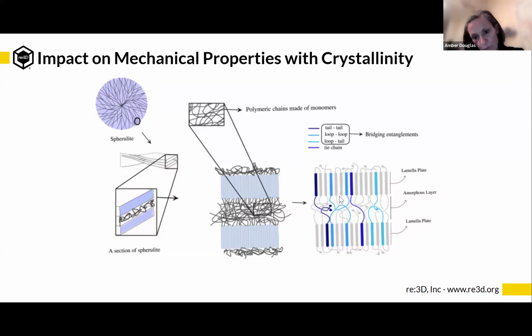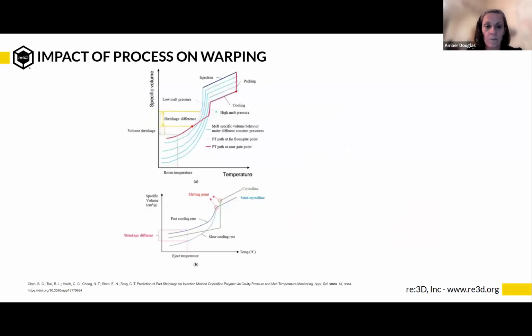But if you imagine trying to break that or pull that apart and do elongation, it's going to act like a crosslink almost. It's not going to break as easy as amorphous. I included this because this is how your process can affect your crystallinity, and they show different parameters that they've set things to. For example, they have fast cooling rate, slow cooling rate down here. And almost anything that you do with temperature or rate of anything is going to increase or decrease your crystallinity. And you want to think about that ahead of time, probably.